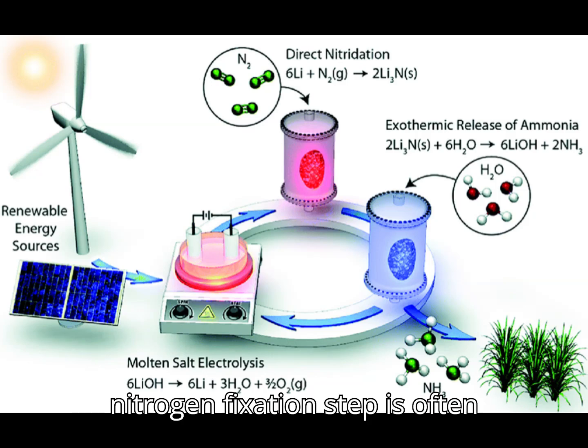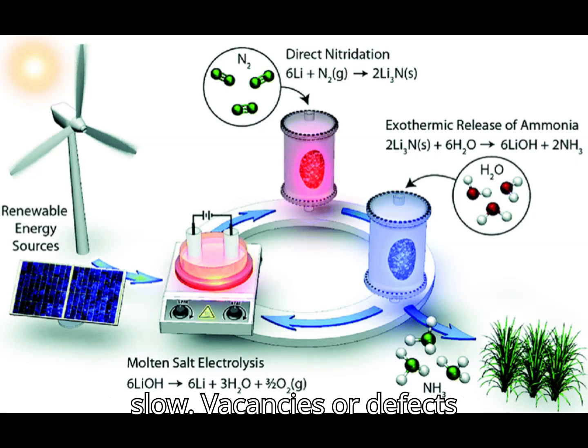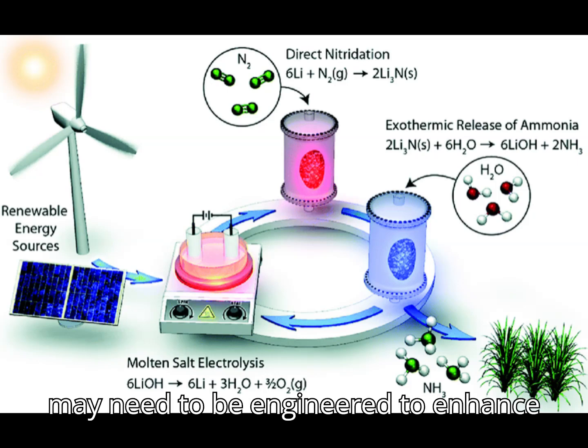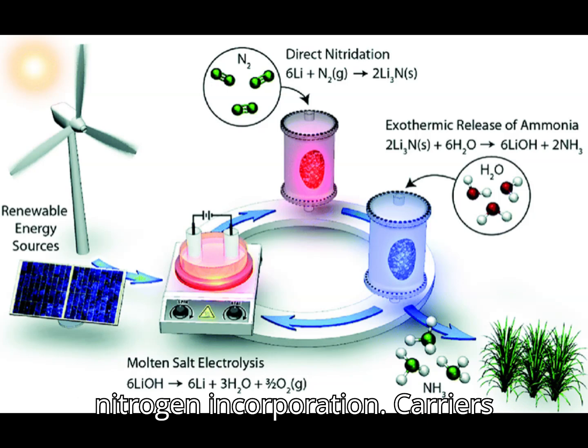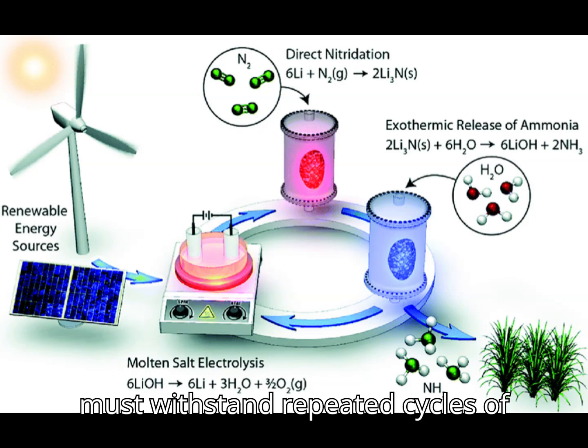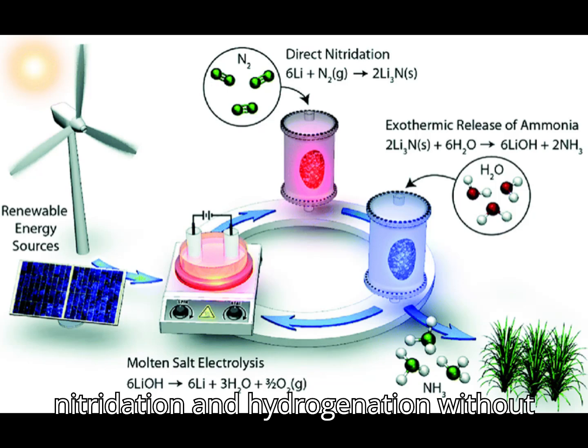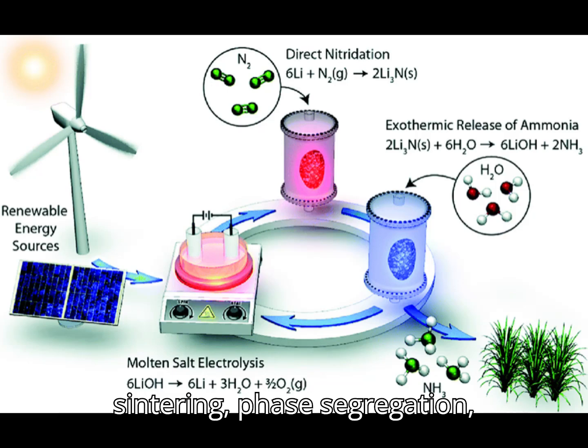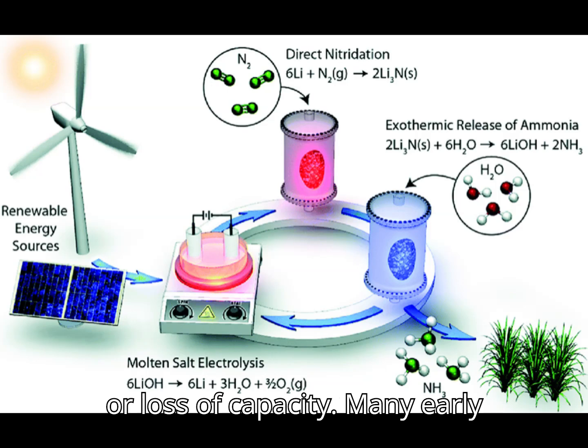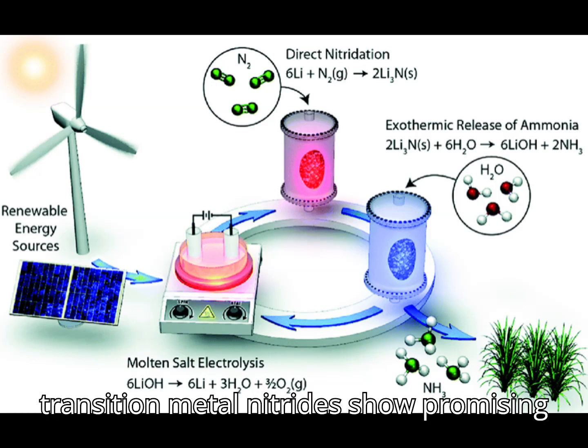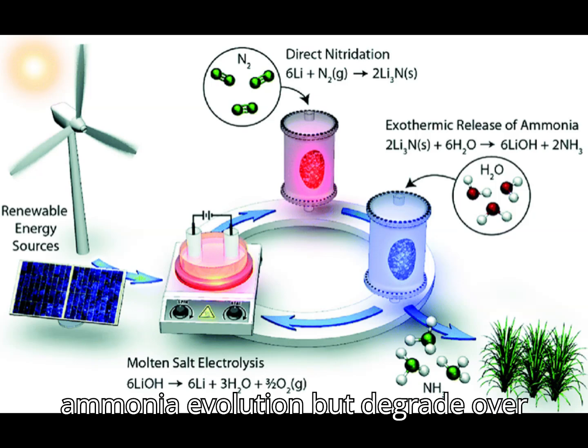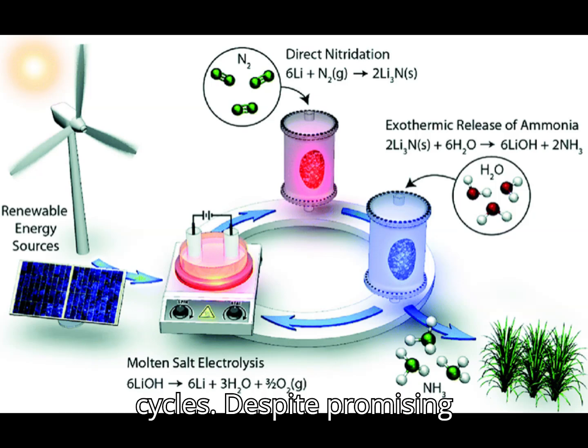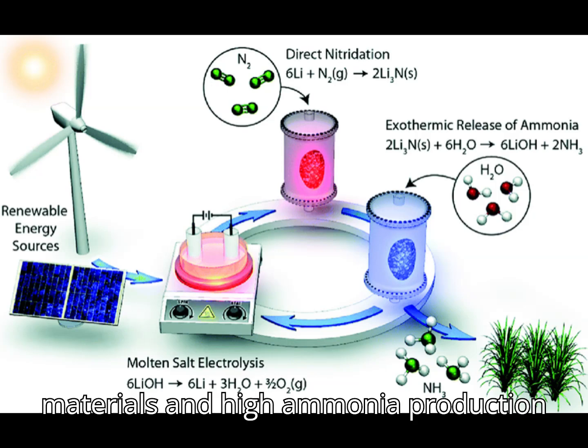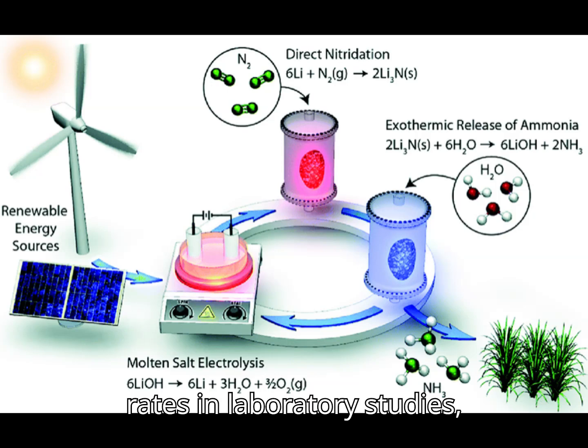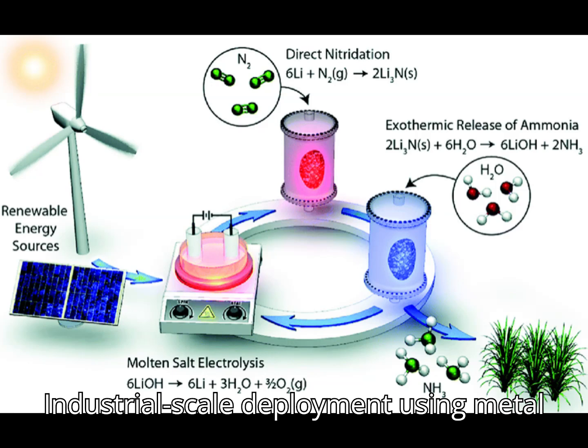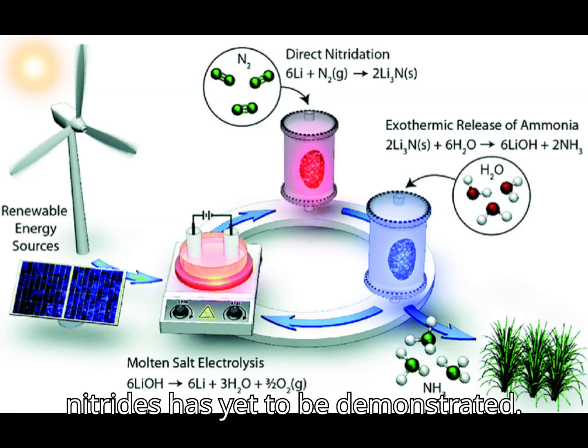The nitrogen fixation step is often slow. Vacancies or defects may need to be engineered to enhance nitrogen incorporation. Carriers must withstand repeated cycles of nitridation and hydrogenation without sintering, phase segregation, or loss of capacity. Many early transition metal nitrides show promising ammonia evolution but degrade over cycles. Despite promising materials and high ammonia production rates in laboratory studies, industrial-scale deployment using metal nitrides has yet to be demonstrated.